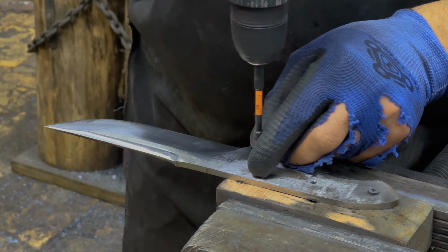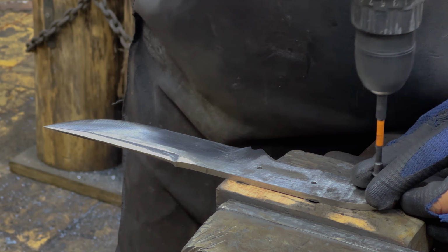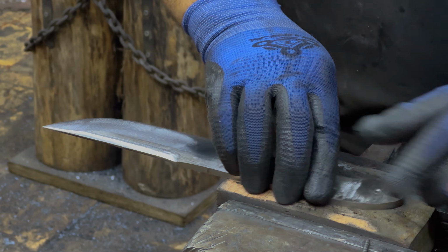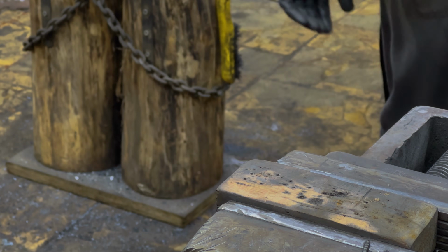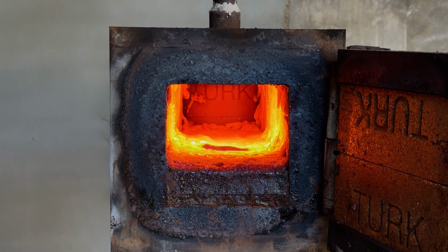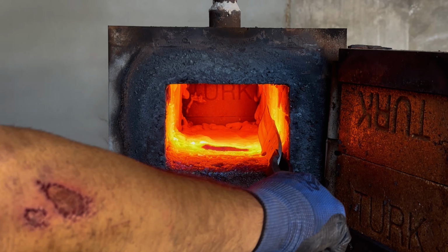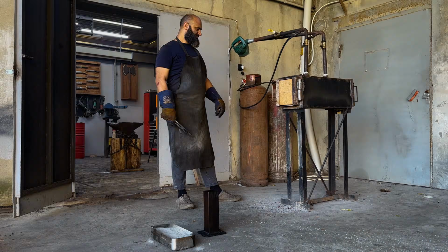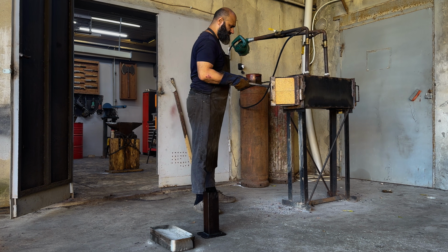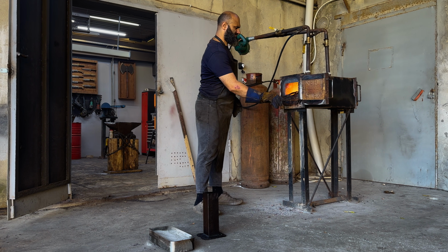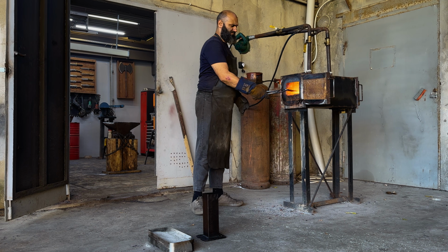Backing out that temporary screw. The blade profile is dialed in, meaning it's finally time for the most stressful part of any build, the heat treatment. Slide the naked blade into the forge furnace. We need to heat it up evenly to non-magnetic critical temperature, around 1500 degrees Fahrenheit, so the crystalline structure of the carbon steel is ready to harden.